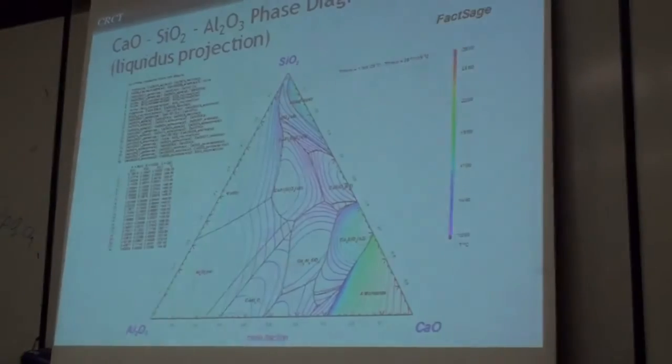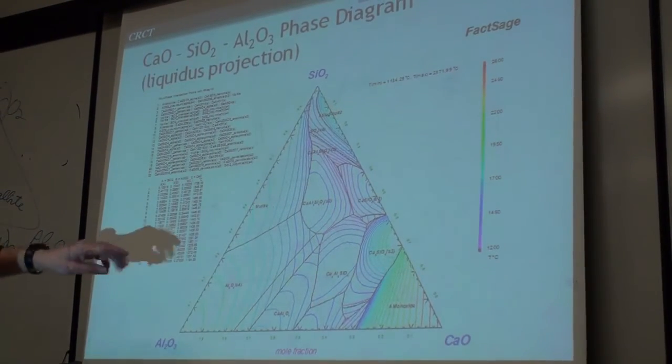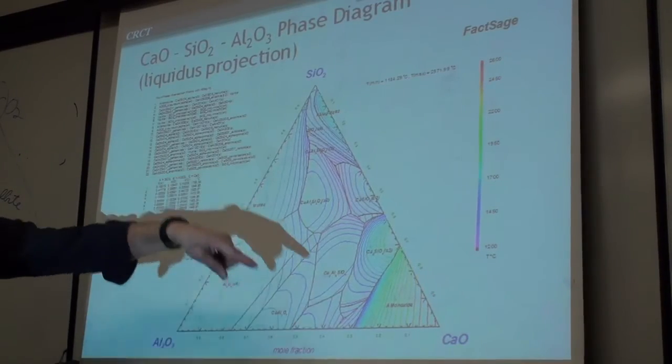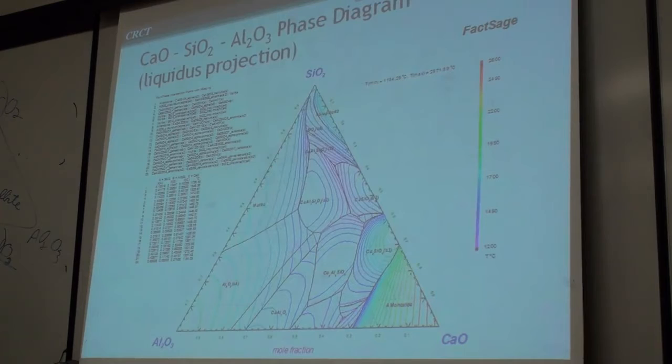There's your calcium silicon. Remember I said the calcium oxide is much less of a charge compensator. So again you can see here, there's calcium. If that were sodium, this would be coming down really, really fast. It just isn't here. The charge compensation factor is much, much less when you have a divalent, because you need 2 calciums to compensate the charge.